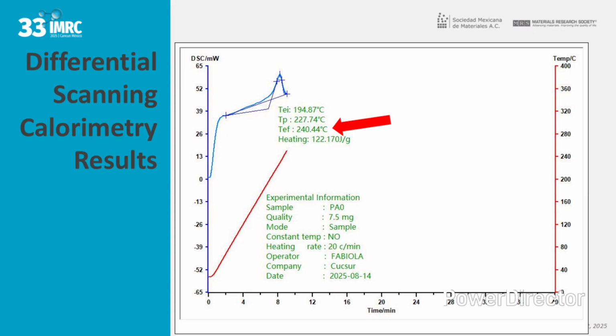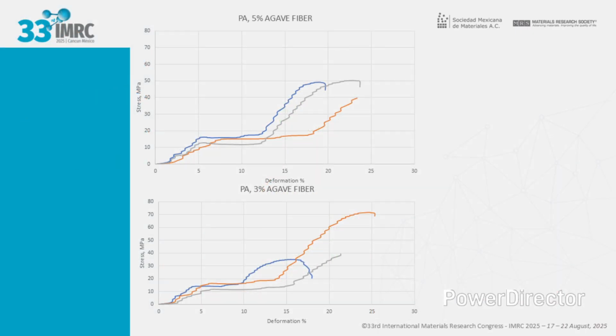and molecularly mobile. The graph shows the stress-strain curves obtained from tensile tests for polyamide, PA, with the addition of 3% and 5% by weight of agave fiber. Each color corresponds to a different specimen as an experimental replicate, allowing for evaluation of the dispersion of results and the reproducibility of the reinforcement.